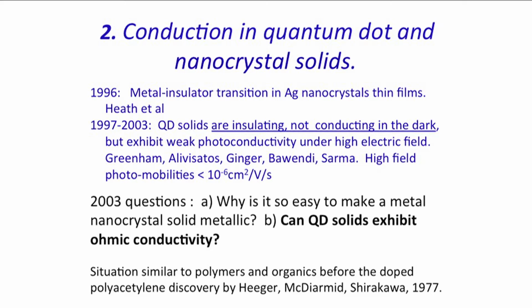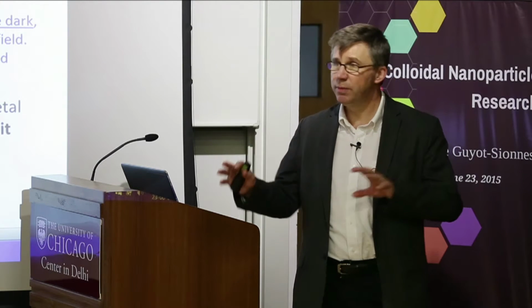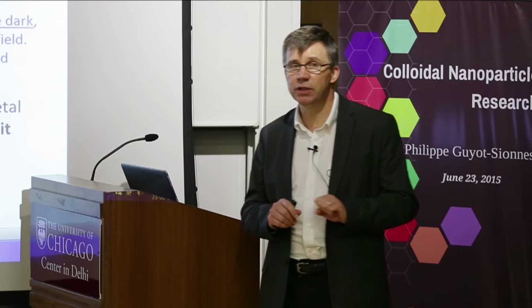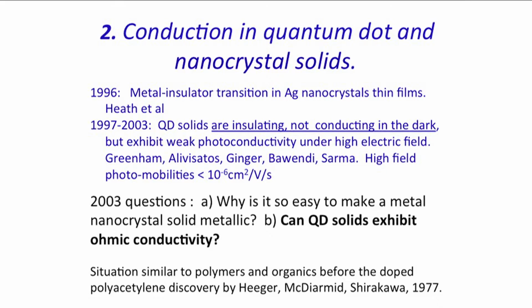One of the first significant observations was the work of Jim Heath, who realized that you could take silver nanoparticles and put them into a film and compress the film, so increase presumably the interaction between the silver particles, and it went from being insulating to metallic. And you could see this in the reflectivity of the film, which was initially not particularly reflective and suddenly turned very silvery upon compression. So that was very striking, and it raised a lot of questions.